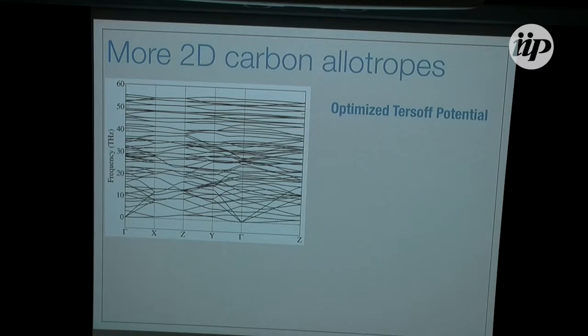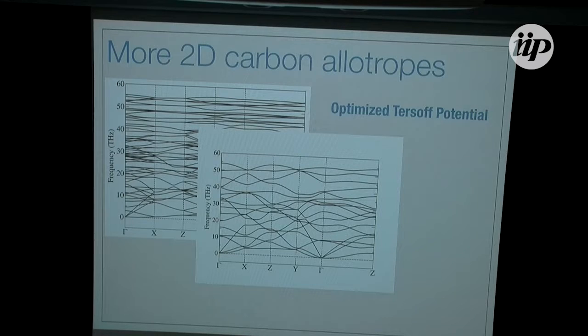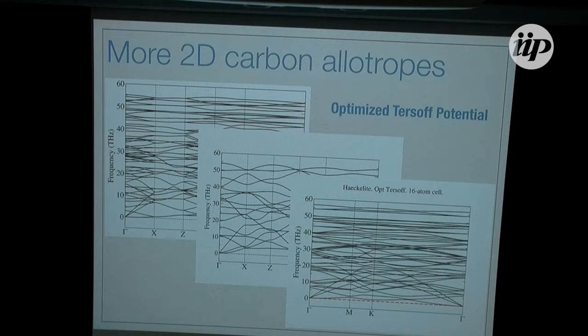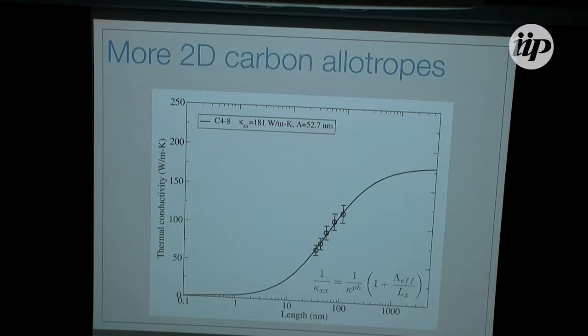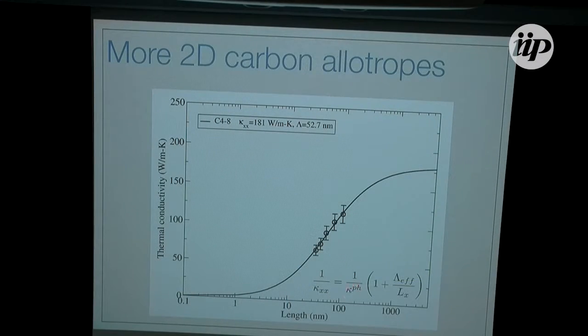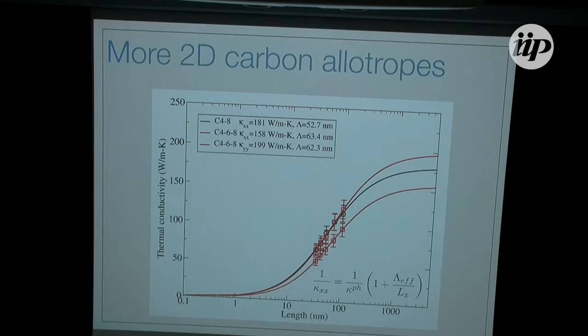Again, we go on and look at phonon dispersions. We see no negative frequencies, so we know we can use our potentials. And then first I calculate the thermal conductivity as a function of the system length. The data points are simulations, and this curve is a fit with this expression, from which I extract the intrinsic phonon thermal conductivity and this average phonon mean free path.